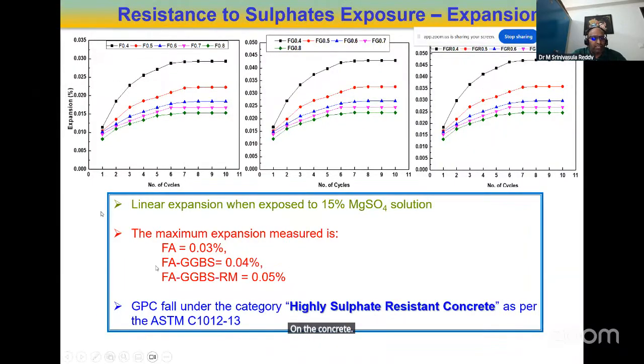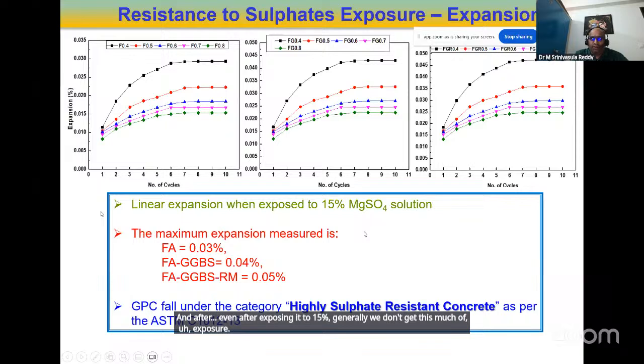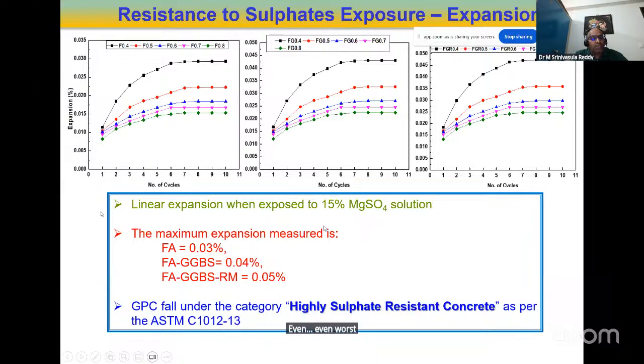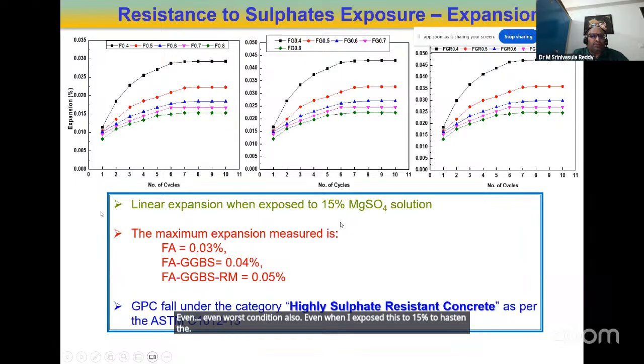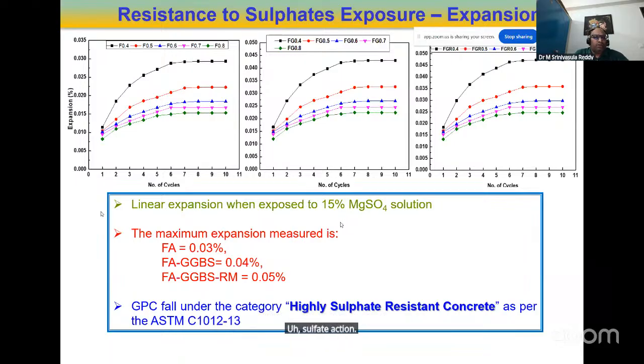So overall, there is not much effect on the concrete. You can see maximum expansion is 0.03, and even after exposing to 15%, generally we don't get this much exposure. Even in the worst condition. Even when I exposed this to 15% to hasten the sulfate action, what I observed is a very small amount, 0.03% and 0.04% only, which will come under highly sulfate resistant concrete.